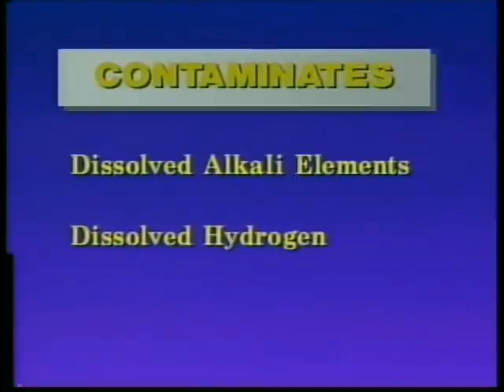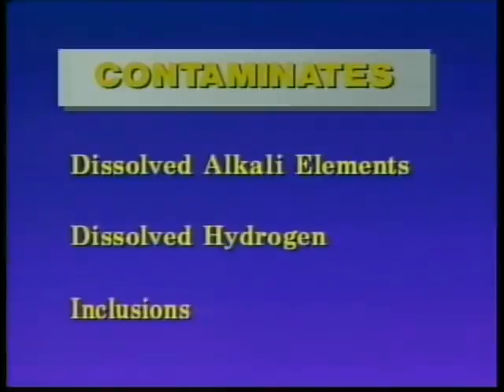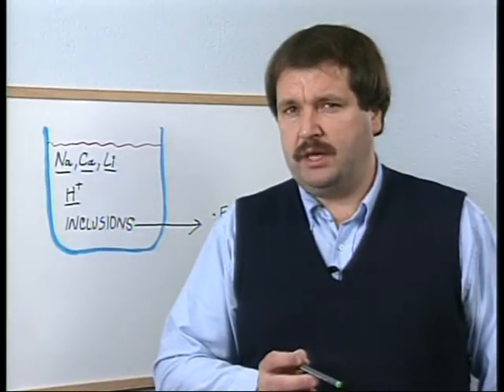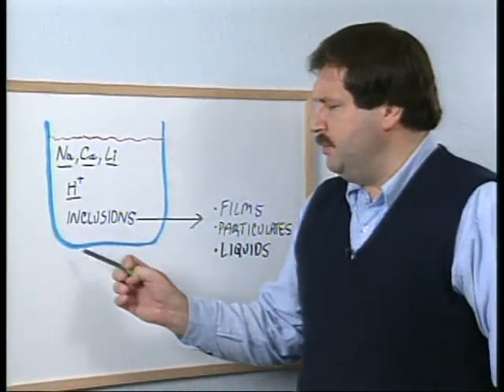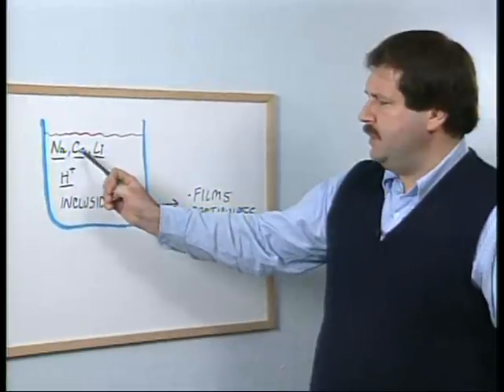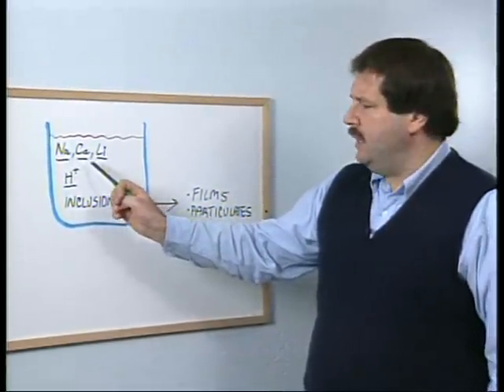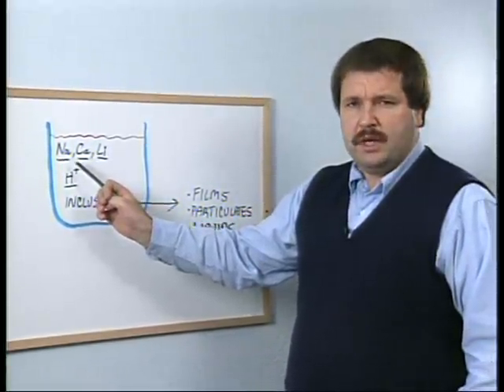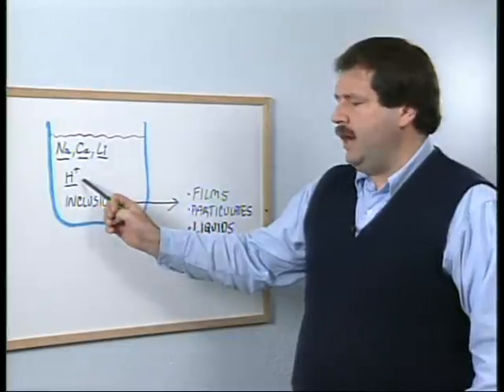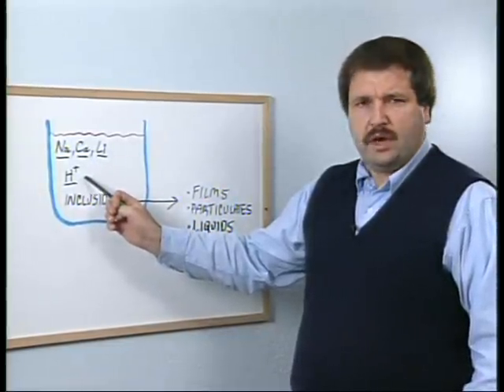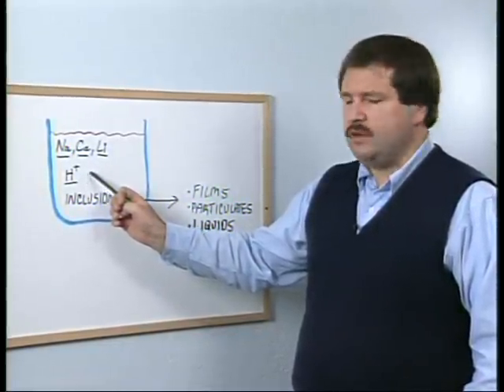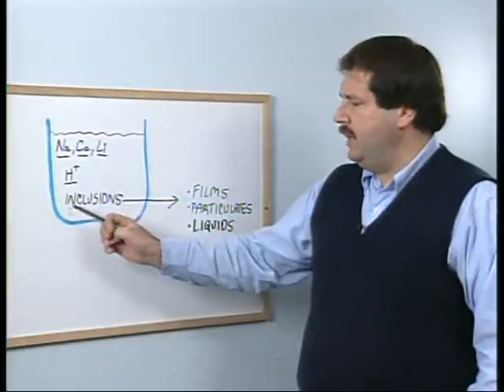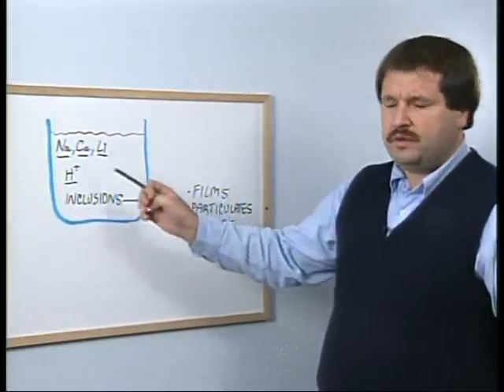Secondly, dissolved hydrogen, hydrogen being the only gas with any significant solubility in molten aluminum. And third are the suspended solids such as inclusions, both nonmetallic and intermetallic. And in this depiction of an aluminum melt, we can see that sodium, calcium, and lithium are dissolved species and arise from pot room metal contamination or scrap contamination. Hydrogen is present as essentially protons because it's ionized, and the electrons are shared by the electron sea of the metal. And then finally we have inclusions that are dispersed throughout the melt.